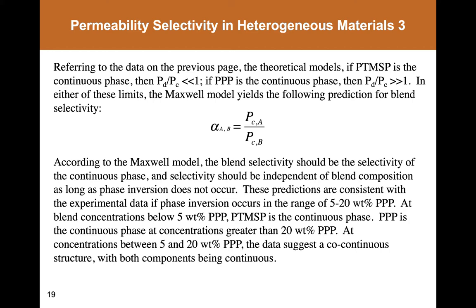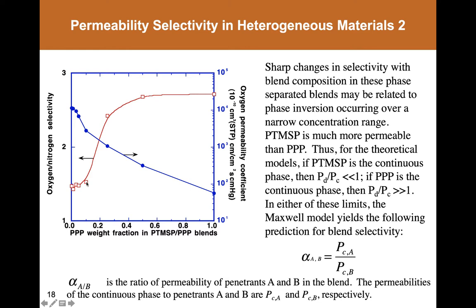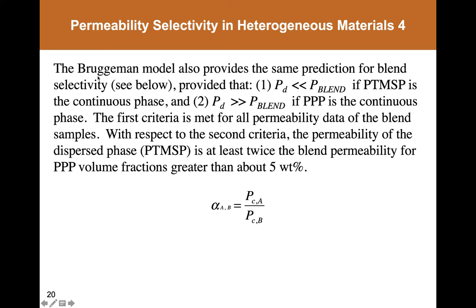in the intervening region, one likely has a co-continuous structure where both PTMSP and polyphenylpropyne are connected in their domains and span the entire sample, so that penetrants can go separately through a pure polyphenylpropyne phase or through a pure PTMSP phase. The Bruggeman model, like the Maxwell model, will also show the same sort of prediction that the selectivity can be dominated by the selectivity of the continuous phase.